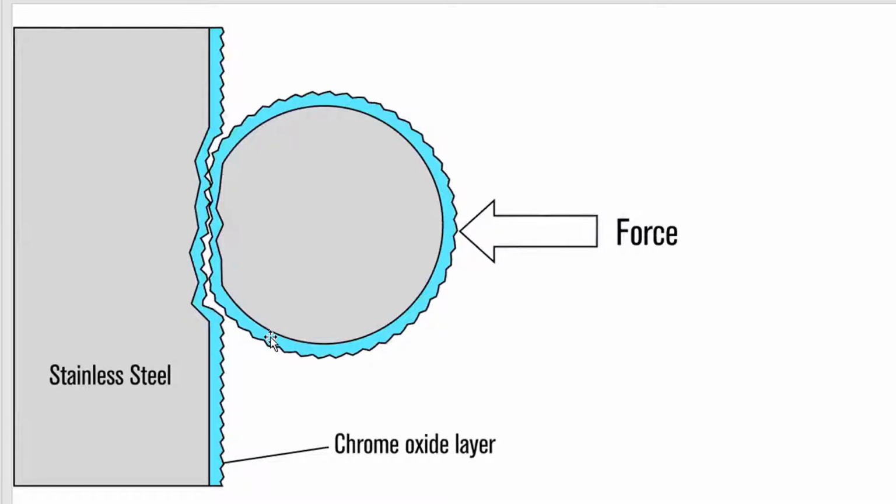Which is interesting. If you called into the spray coating webinar, I showed you what that stripe looks like on parts that we have intentionally coated in chrome oxide. And if you'll notice, it's black. Well, there's a very thin layer of chrome oxide on the stainless steel, so why doesn't it look black? The reason it doesn't look black is because that chrome oxide is so thin that it allows some light to just go through the layer, refract off this shiny stainless steel, and reflect outwards.